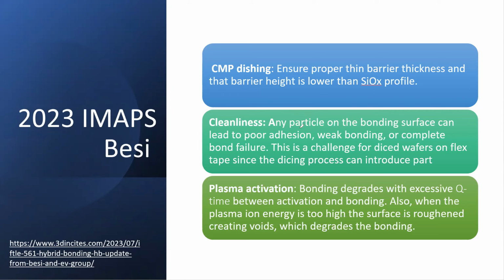And then from the high volume manufacturing perspective, cleanliness is key. Any particle on the bonding surface, you will get poor adhesion, weak bonding, complete bond failure. This is a challenge for die-to-wafer. And you will see that BESI did a reasonably good job here, but EVG, the other supplier, had problems. They couldn't overcome this problem, so the yield is low.